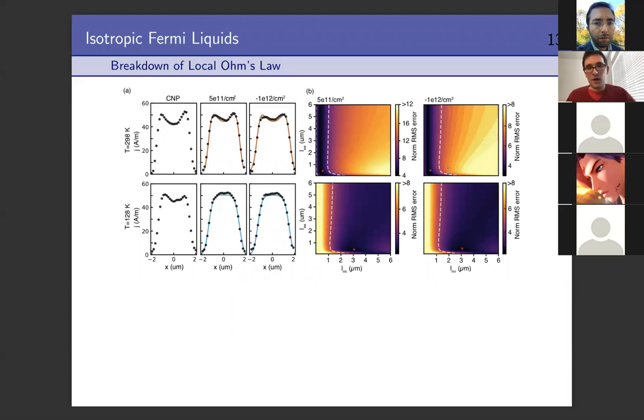And these top 2 plots confirm for us that we are definitely ohmic. Okay, there's a very short electron momentum relaxing mean free path. And the mean free path that pops out of the simulations is essentially what we measure independently through a bulk transport measurement. So this image is quantitatively consistent with what we would have predicted.